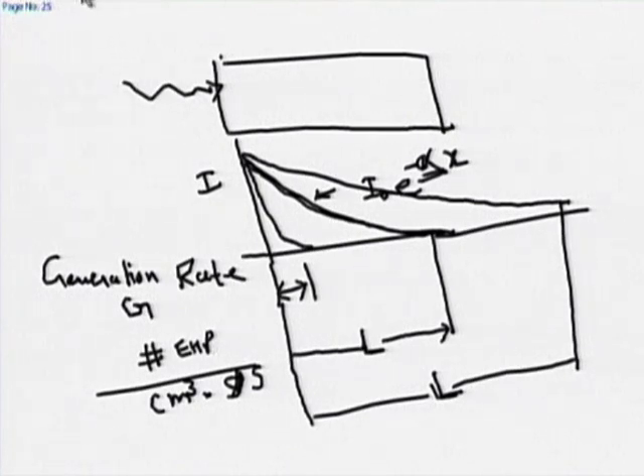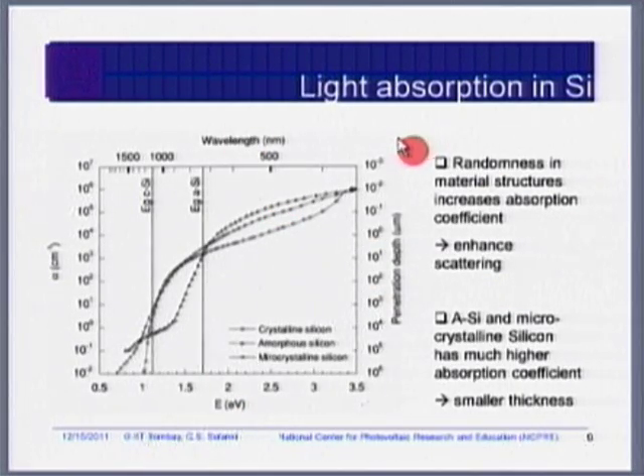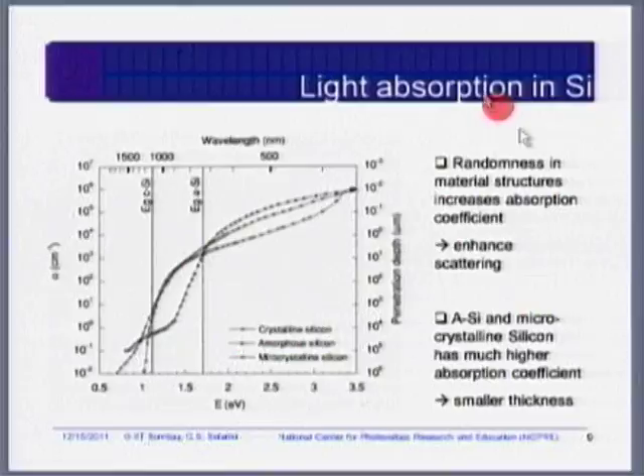Generation rate is the number of carriers per unit volume per unit time. Absorption coefficient is also shown for various silicon materials. Amorphous silicon acts as a direct band gap semiconductor, so a very thin layer is required. Crystalline silicon acts as an indirect band gap semiconductor. Commercially, crystalline silicon cell thickness is 180 microns, but amorphous silicon cell thickness is 1 micron or even less. Because amorphous silicon is a disordered material with many defects, there is more scattering of light, making absorption stronger and absorption coefficient higher.